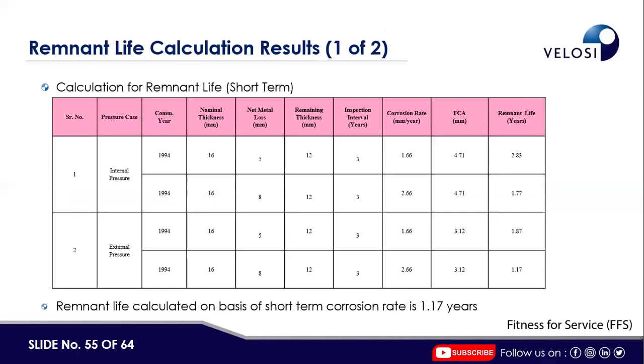So life calculations are based on API 571 and 510 criteria. You can see the net metal loss for internal pressure and external pressure, for the short-term corrosion rate and long-term corrosion rate. The nominal thickness was 16 mm, net metal loss 5 mm, 8 mm. When we say 8 and 8, these repairs were basically done. And the remaining thickness reported after repairs was 12 mm. Inspection interval 3 years, corrosion rate from previous inspection to new short term is 1.66 mm per year, 2.66 mm per year. So FCA 4.71 for internal pressure, 3.12 mm for external pressure.